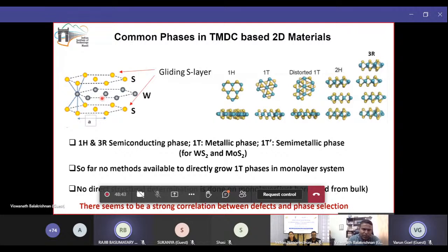However, it is also possible to introduce a small amount of gliding. Imagine you have the top layer or the bottom layer of sulfur slightly glided, which means the top layer of sulfur and bottom layer of sulfur will not coincide in the same position. That way we can achieve other allotropic phases. That is what happens in the case of the 1T phase. The 1T phase is metallic. Then you can also have gliding plus a small amount of distortion in your bond length. Then we call it distorted 1T, otherwise 1T prime. It is essentially a semi-metallic phase. So we can have metallic, insulating or semiconducting, and semi-metallic phases, all of them just by manipulating the structure.